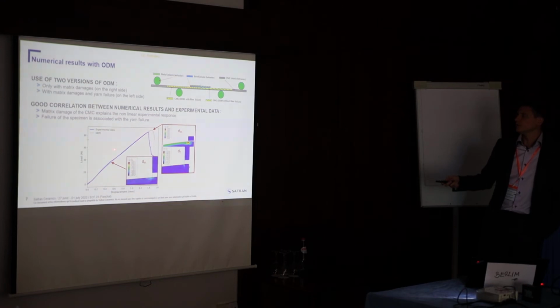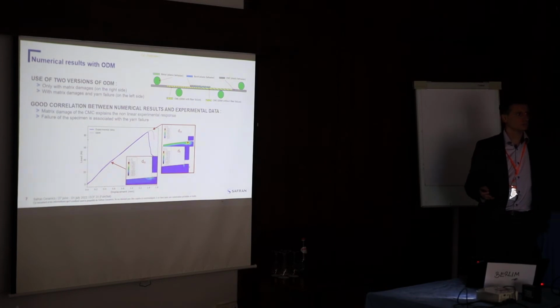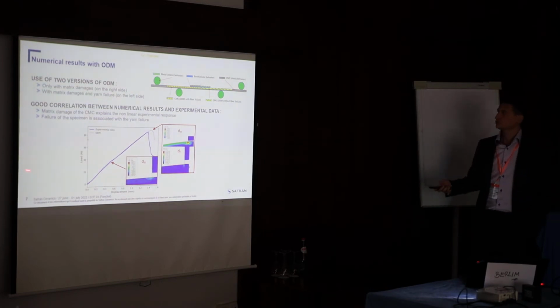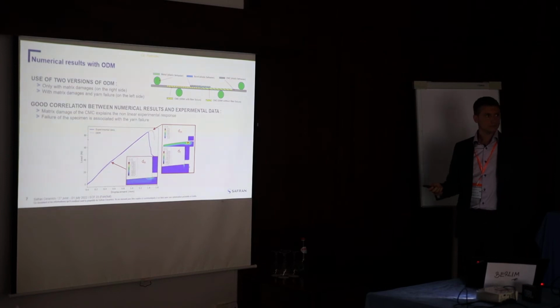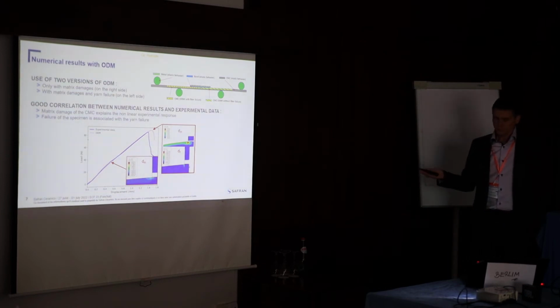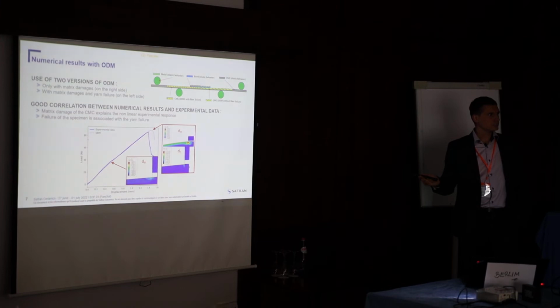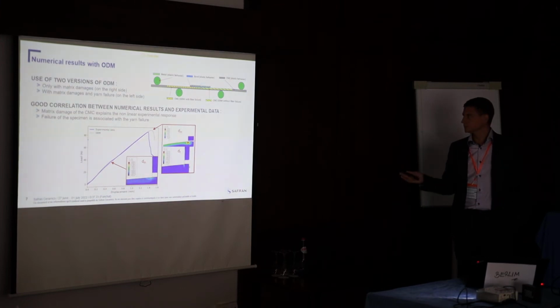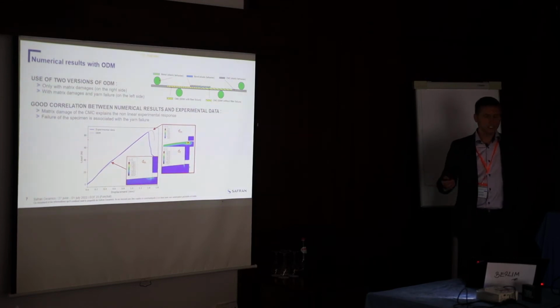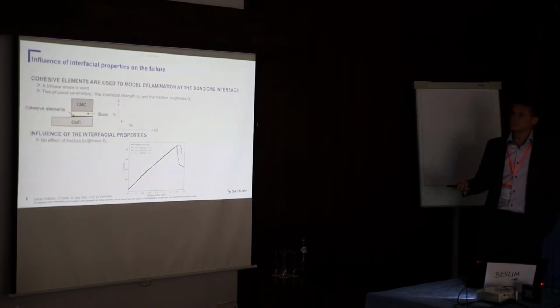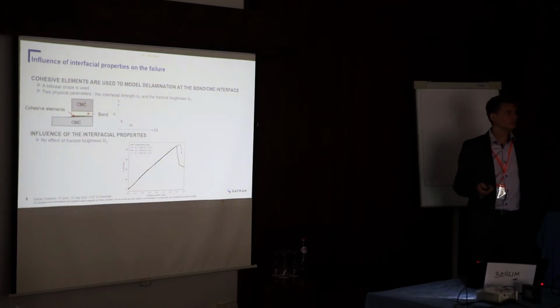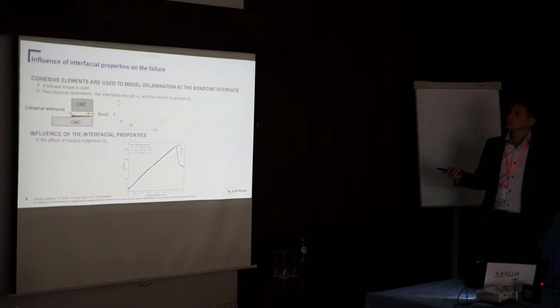So we are not able to predict exactly what we have seen in the experimental test, but we are able to describe the phenomenon and the damage mechanisms. So we can be satisfied by this result, but not exactly, because we don't know why we don't have delamination before yarn failure. So we have performed other simulations using cohesive elements. So we added cohesive elements between the bond and the CMC substrate.